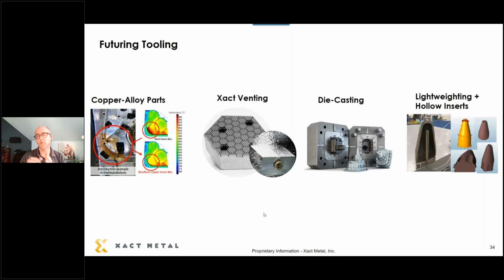But then I added liquid CO2 to it to help cool it down. Liquid CO2 does a phase change: as soon as it hits atmosphere, it rapidly expands and becomes about negative 109 degrees Fahrenheit. So I was actually able to take the cycle time from the conformal cooled at 40 seconds down to 35 seconds. So I knocked another 5 seconds off that cycle time by doing something completely different. And the cool thing about the liquid CO2 is it evaporates, so you don't have to worry about water residue or rusting. So it's some cool stuff.